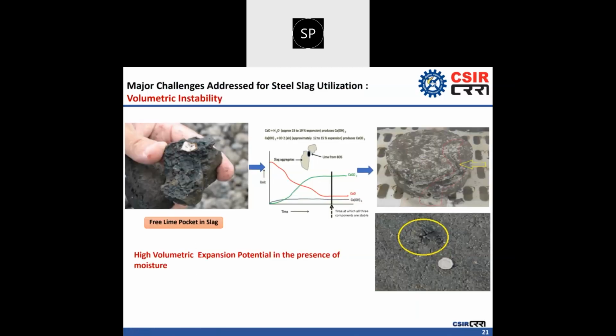Now, what are the challenges associated with the steel slag utilization? As we discussed in the previous slide, the steel slag contains free lime, which can cause volumetric expansion if the untreated slag is utilized for the preparation of bituminous mix, or in the unbound layer or granular layer. So in order to reduce this free lime content to less than 3 to 4%, we have to subject the steel slag to weathering or aging treatment.